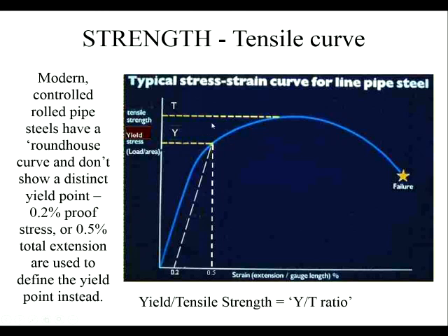So if you like, the safety margin that we had in hand with the material is much less, but the strength is much greater. So we've got a material which has much better properties, but our extra strength in hand is much less, so the safety limits are much more difficult. And sometimes we therefore try to define this yield strength divided by tensile strength ratio, the so-called Y over T ratio, as another parameter we might want to specify.